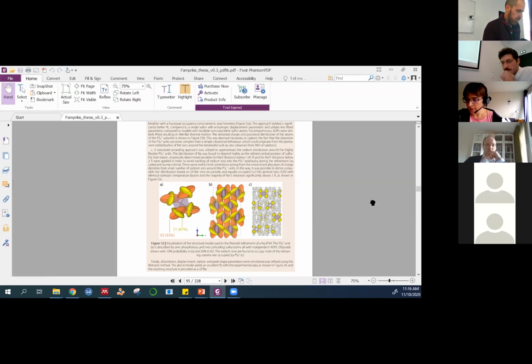If I sum all occupancy, I see that you get the right stoichiometry, so you put this as a constraint. But I have no idea if you would refine all parameters at the same time. It gives a huge number of refined parameters. Is it still plausible regarding the number of reflections, given that you only have powder data? So you have limitations. You probably need several reflections to refine one parameter. So can you comment about this?